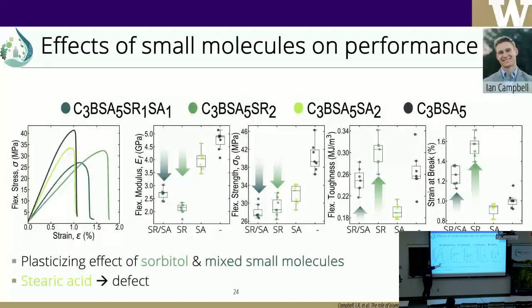Now, in our mechanical properties, these are again flexural tests, and the convention that you see here is that the numbers correspond to the weight ratio for each of the components. C is going to be our cellulose, BSA our protein, sorbitol is going to be our low molecular weight sugar, a carbohydrate, and then stearic acid our fatty acid. So you see that we have a 3-to-5 ratio between cellulose and BSA. That reflects our spirulina concentration. And then we have 10 and 10% of the small molecules.